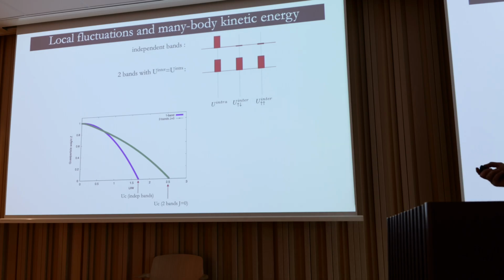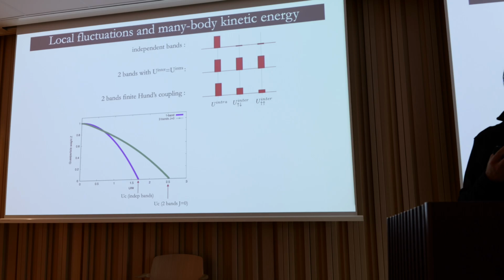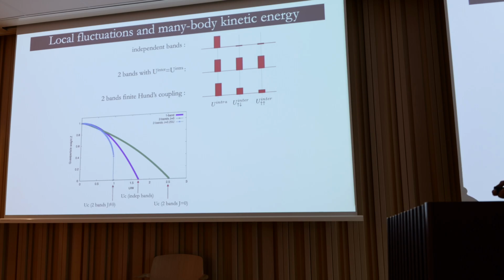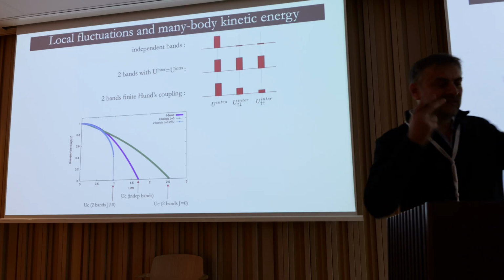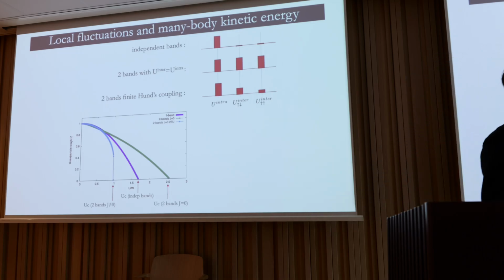And if you now reduce part of the interaction, as we do with the Hund's coupling—reducing the interorbital interaction, and even more if you have parallel spins—you might think, okay, now I've reduced the interaction, so I should have a more weakly correlated model. You get the opposite: the Mott transition arrives very fast, even faster than in the single-band case. So it's counterintuitive, and it really tells you that you cannot...